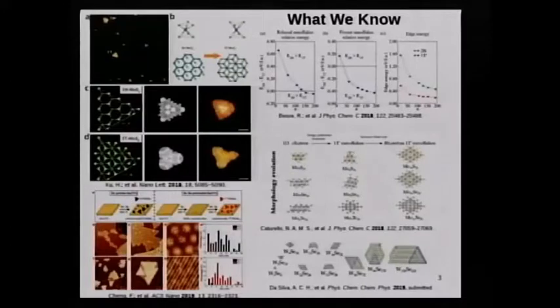We have established in this first paper that the edge formation energy, which is the energy of a particular relaxed nanoflake minus the energy of the periodic phase, is the main factor that stabilizes 1T prime nanoflakes in relation to their 2H counterparts in the smaller sizes.